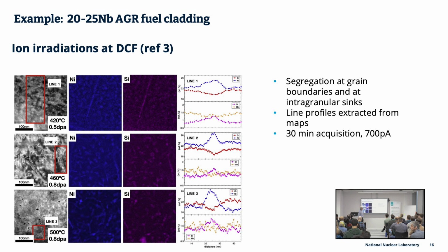You can see that there's also segregation of nickel and silicon, particularly to defects within the matrix either side of the grain boundary. And because this was, I think, a 128 pixel square map, even though a half an hour acquisition, it means that there's a reasonable amount of noise and scatter in these plots.